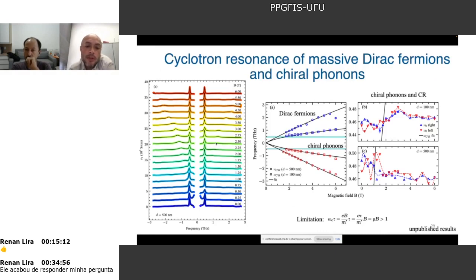And then we want to study two things. First, the dispersion, frequency as a function of magnetic field, for these carriers, and they follow a square root of B function, right? And for both samples, you can see here that when I move from this circle to the square, meaning from 500 to 100, this is 500, this is 100, there is a change in the electron levels that I'm measuring. And also we can study the interaction between these chiral phonons and the cyclotron resonance, right? And it's still not clear what the effect is. It looks like something happened in this crossing, but we still don't know the real effect of this interaction.